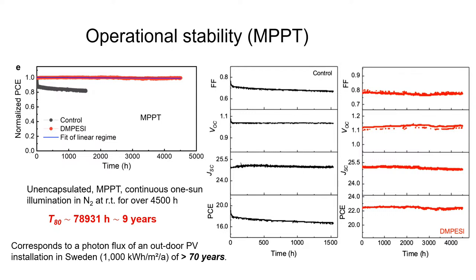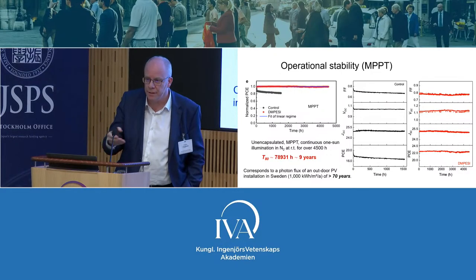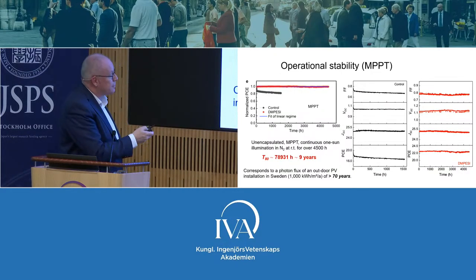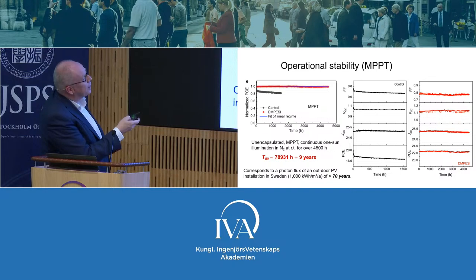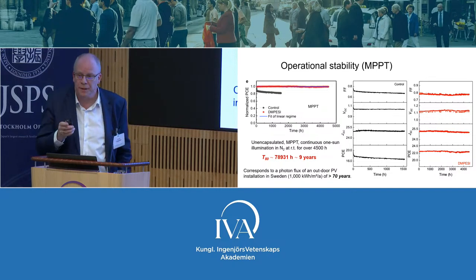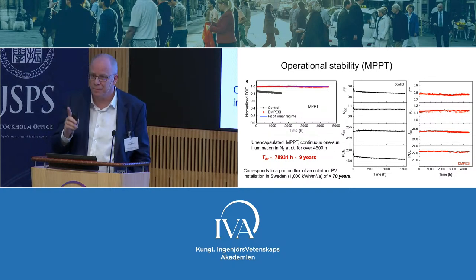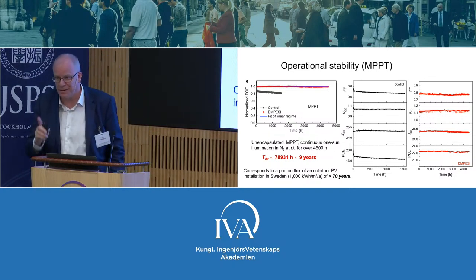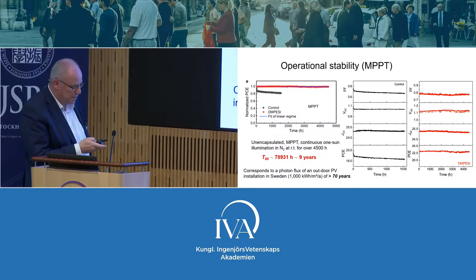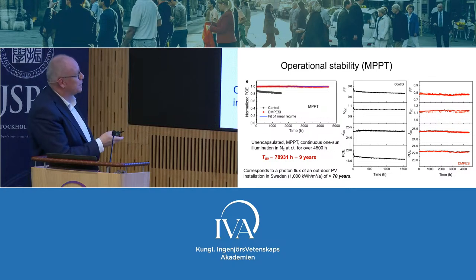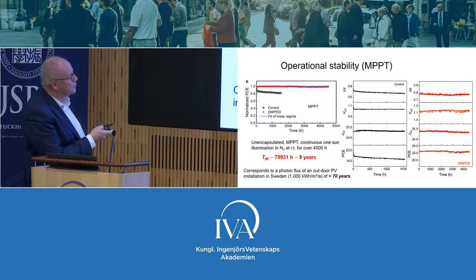This is now measured continuously, so it is under load 24/7 for almost 5,000 hours, and you see it's a straight line. This is at room temperature, so that I have to admit. We have to do this at 85 degrees as well. And we have done it at 45, but still there are question marks to solve.